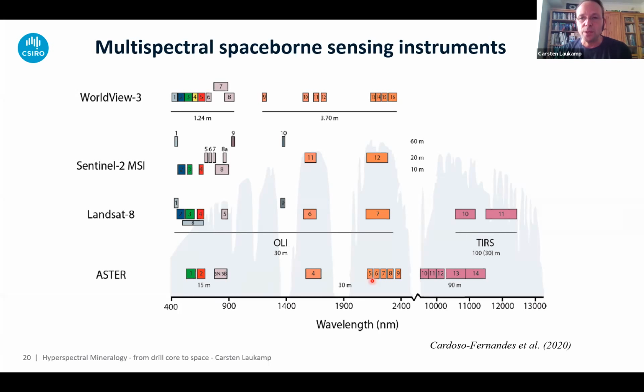It really is designed to map minerals, which is in contrast to Landsat 8, which is used by many people to distinguish minerals, but actually you can't distinguish minerals with Landsat. Sorry, you can map iron oxides with Landsat. That works quite well because we have this band number 5 collected around 900 nanometers. But there's no way to distinguish chlorite from white mica from kaolinite or something like this. That just doesn't work. You might, if you apply some clever machine learning approach, be able to do that, but it's a very case-specific application then. If you use band ratios in ASTER to map out the different minerals, then you can apply that everywhere on the globe, and it should work, actually.